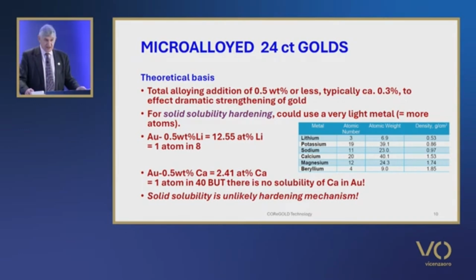If we assume a maximum alloying level of 0.5% and taking the lightest metal in the table, lithium, then a gold 0.5% lithium alloy, for example, is 12.55 atomic percent lithium, which is within the solid solubility range. This is 1 atom of lithium to every 7 atoms of gold.